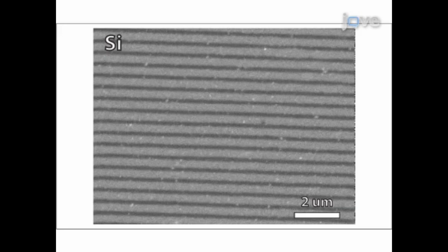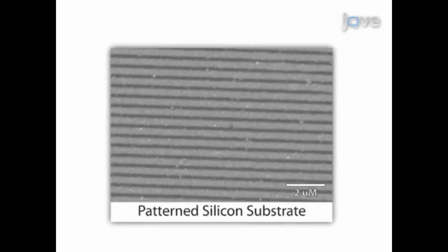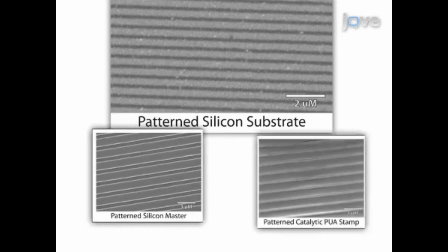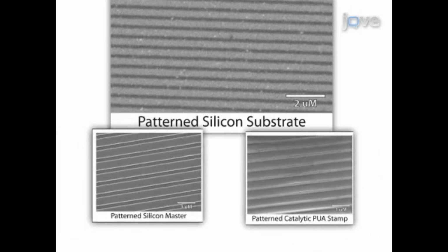Due to the diffusion-free nature of the method, the resolution is close to that of photolithography, as seen in 125 nanometer features. These features were uniformly reproduced across the entire silicon substrate surface. The dimensions of the printed features were identical to those on the corresponding silicon master and the catalytic stamp. Remarkably, the catalytic stamp can be reused multiple times without losing efficiency.